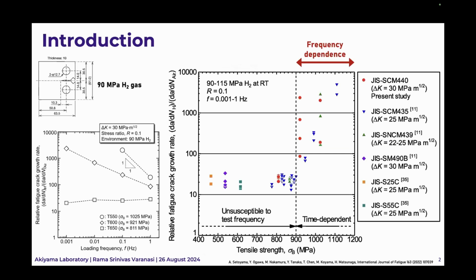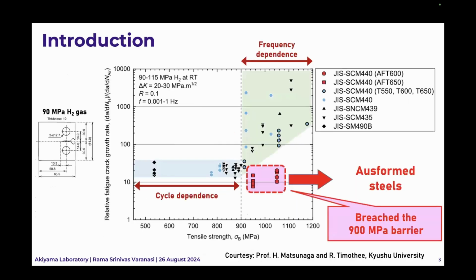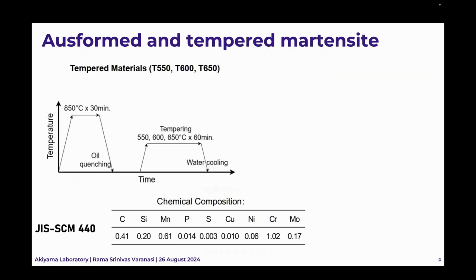And what is ideally required is a cycle dependence rather than a frequency dependence. And this we can refer to as a 900 megapascal barrier. However, recently, Professor Matsunaga's group found a couple of steels, same composition, but with Ausforming, they were able to breach this 900 megapascal barrier. And we can clearly see that there is no frequency dependence, even though the tensile strength is much greater.